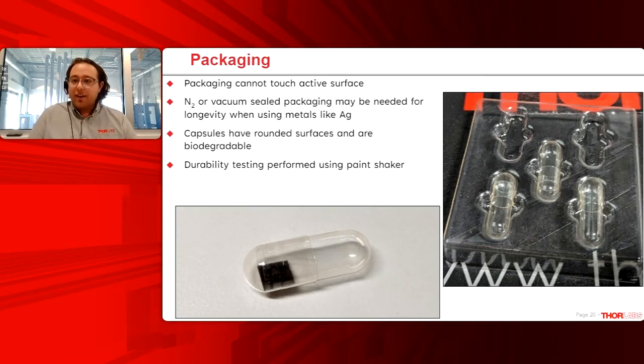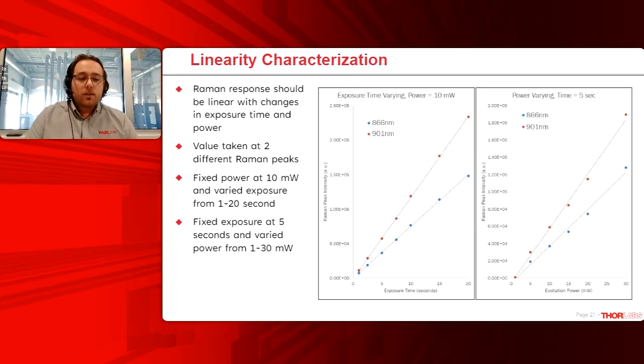So now that we have hopefully characterized all the ways that the chip can get to the customer, we need to take some customer use cases into account. So for this, we ran some linearity characterizations. It is not uncommon when you are doing Raman or SERS testing that maybe the laser power varies a little bit from day to day. Maybe someone changes some of the software settings and changes the integration time. So for this, we want to make sure that our substrates can easily be scaled to some known reference. In this case, we varied the exposure time and fixed the power, and also varied the power and fixed the exposure time. And we did find that there was a linear relation no matter what the power or the exposure time is. So this is really nice for certain applications where maybe those variables aren't consistent, and you could always scale them to a known benchmark.